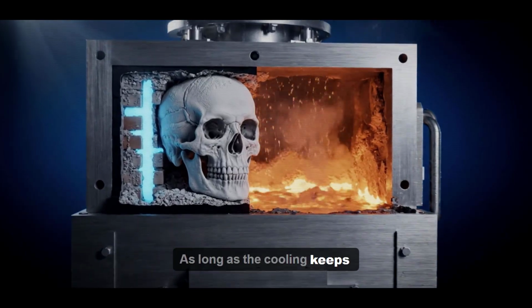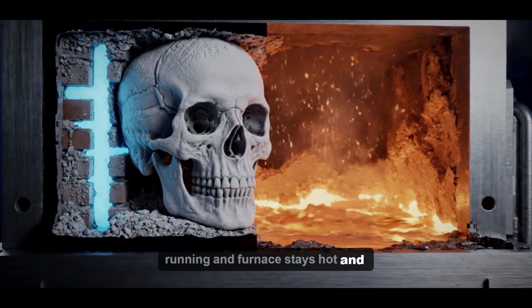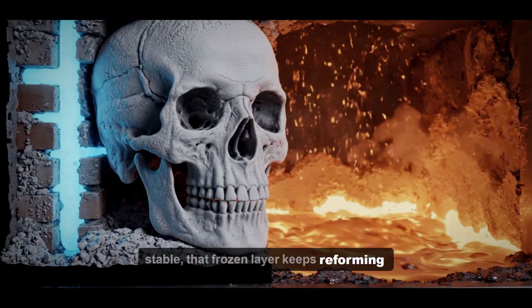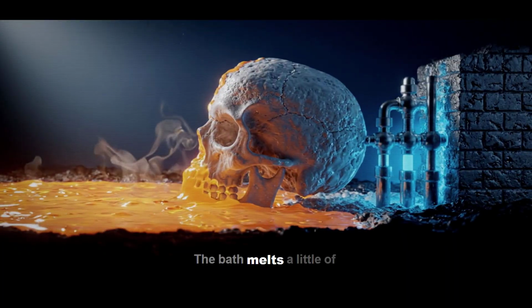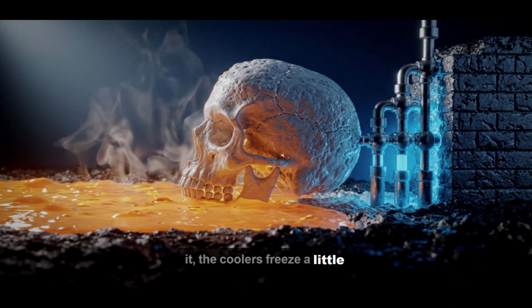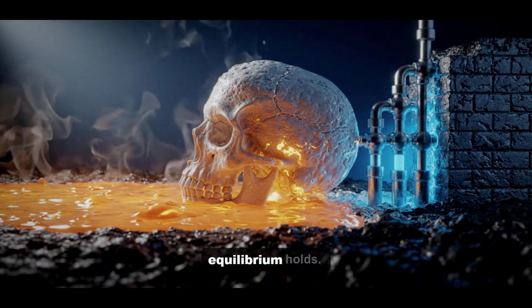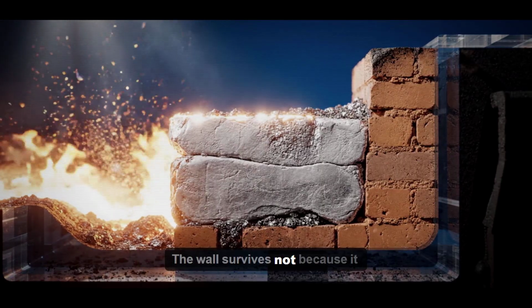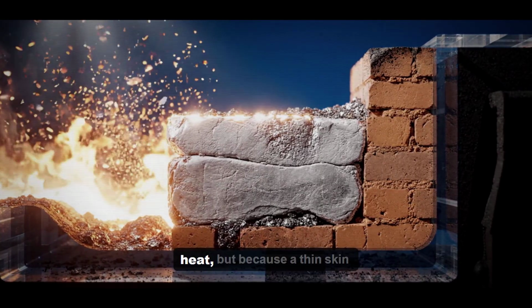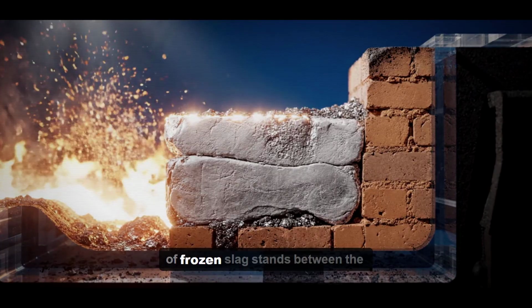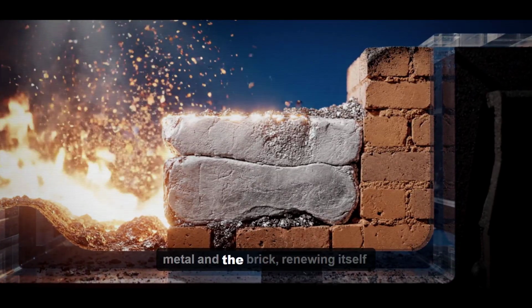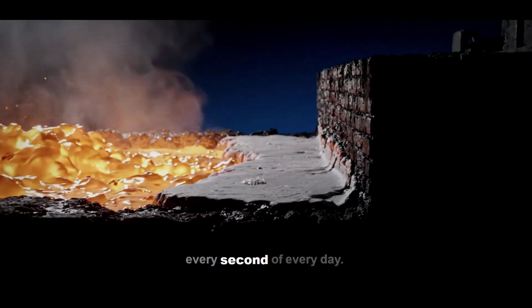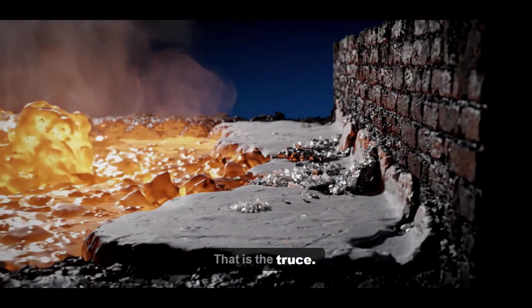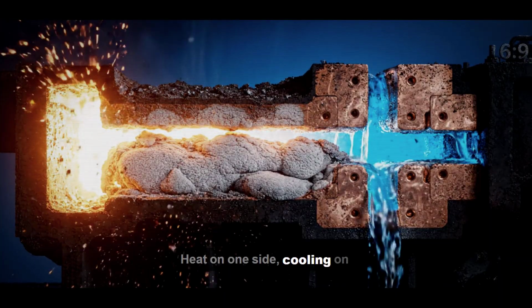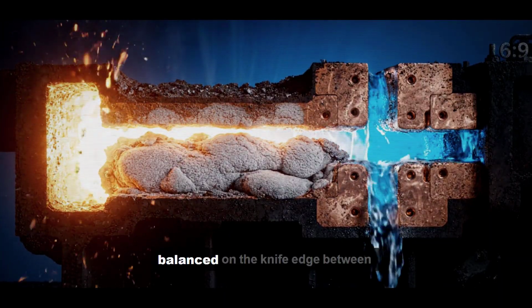As long as the cooling keeps running and the furnace stays hot and stable, that frozen layer keeps reforming itself. The bath melts a little of it, the coolers freeze a little more of it back, and in equilibrium it holds. The wall survives not because it is tough enough to take the heat, but because a thin skin of frozen slag stands between the metal and the brick, renewing itself every second of every day. That is the truce. Heat on one side, cooling on the other, and a frozen shell balanced on the knife edge between them.